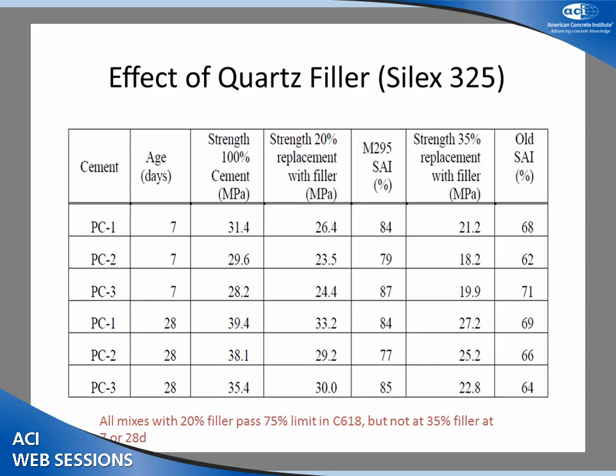Now, if you went to 35% replacement, which is the old activity index test, then those fillers wouldn't pass, because 25% is about optimum for a lot of different fillers. But when you get to higher replacement levels, when there's nothing going on there, then you start to distinguish the non-reactive materials from reactive materials. So one of the big problems was that switch from 35% to 20%, which is about 15 years ago or more.